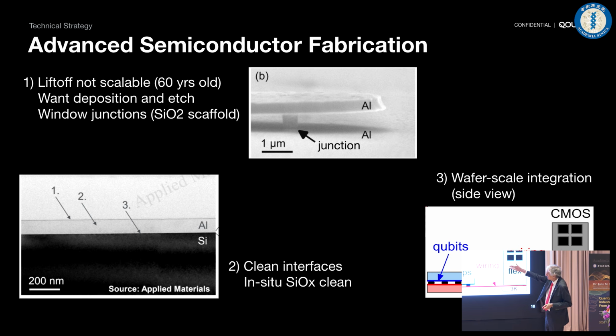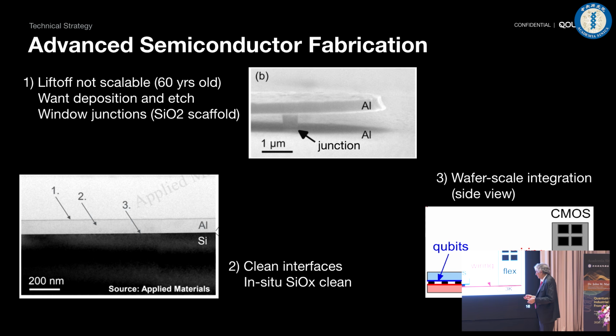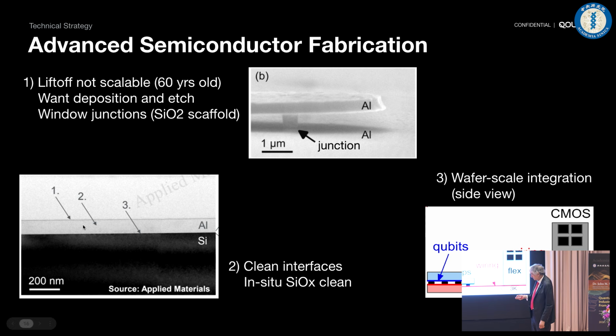Another example here, and this is from Applied Materials, is how we deposit our aluminum on silicon. When we do aluminum on silicon, the interface between the aluminum and silicon has to be atomically clean, and they can do it so that they can put the silicon in their device, clean off the surface in vacuum, and then put aluminum on top for a very good interface. That's clean. The other thing they can do is grow the aluminum in a very uniform way. These are basically single crystal aluminum devices, tens of microns across, and making this very flat will enable us to make more reliable Josephson junctions. So Applied Materials knows how to do this.